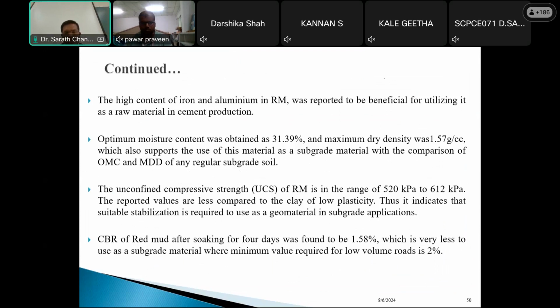The UCS of red mud is in the range of 520 kPa to 612 kPa. The reported values are less compared to clay of low plasticity. If you look at any clay of low plasticity, the values will be much higher than red mud. Thus, it indicates that suitable stabilization is required to use it in geotechnical applications. CBR of red mud after soaking for 4 days was found to be 1.58%, which is very low to use as a subgrade material, where the minimum value required for low volume roads is also 2%.